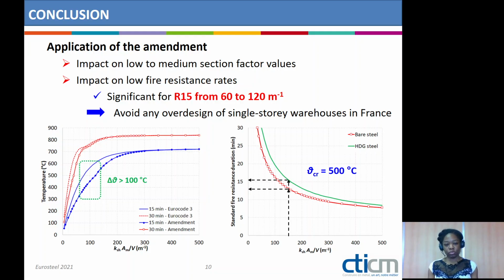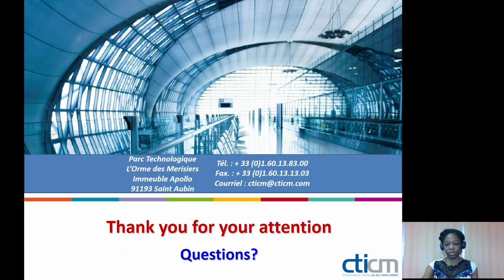So in order to answer the initial question regarding the possibility to have a protective coating against both corrosion on the one hand and fire exposure on the other hand, you can see that it can be done with hot dip galvanizing, provided you want to meet low fire resistance rates and you have low to medium section factor values. It's definitely not an alternative to existing passive protection solutions, but well, in certain cases, it can be quite an alternative to usual, traditional design.